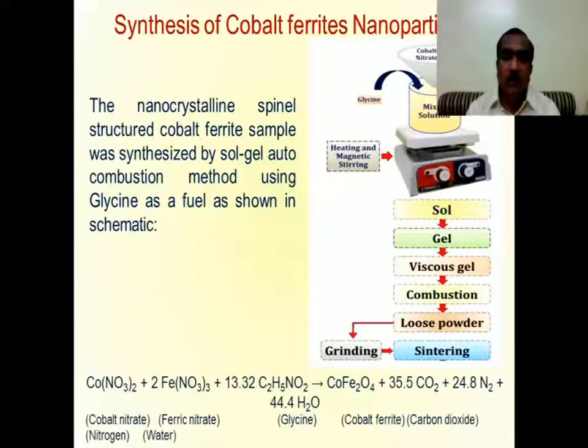So these are some basic parameters of the synthesis procedure. Here is the synthesis procedure. You can see the different steps involved in this process. You can see the magnetic stirrer on which a beaker is placed, in which we use the cobalt nitrate, ferric nitrate, then glycine as a fuel, which is simultaneously stirred and heated. Then we find that there is formation of sol. After some time we find the gel is formed, a viscous gel, then combustion takes place, and lastly we observe the loose powder. And once we get the loose powder, it is dried and then ground, and lastly sintered in a heating chamber or in a furnace.